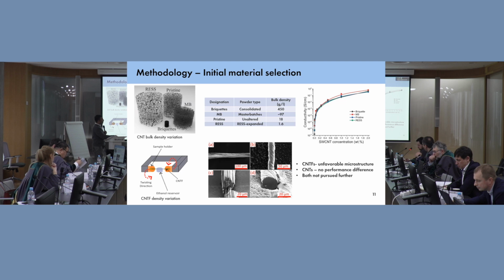So we wanted to go, because we wanted to understand the mechanism of working, we wanted to see repeatability, we wanted to see all factors which are free of this variance. So we went with slightly higher weight percentages where our variance becomes much smaller. So at least we remove this to understand, is this from our different batches that we're processing? Because our equipment does have a limitation. We can't process a lot of volume at the same time.